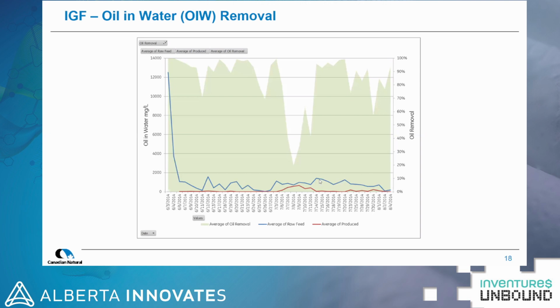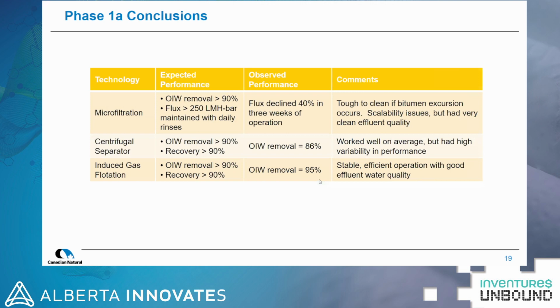So the IGF was the clear winner out of this evaluation. It met our oil removal requirements. It was stable. It was efficient. The centrifugal separator worked fairly well. Not as stable. There's variability in its performance. And the microfilter really didn't work very well at all. There were a lot of operational issues, and we never were able to achieve stable performance.